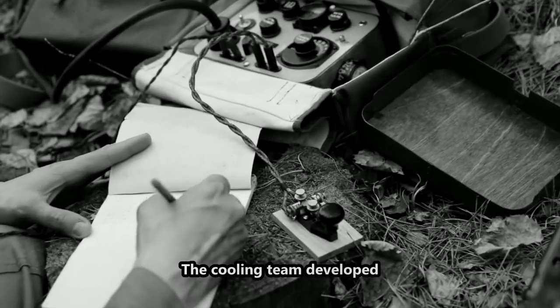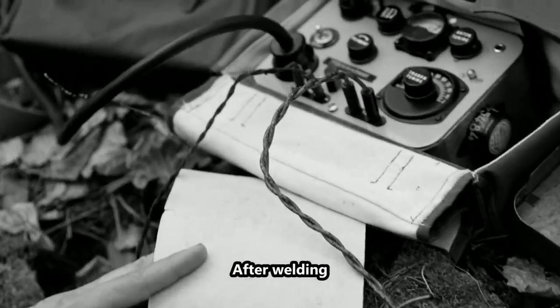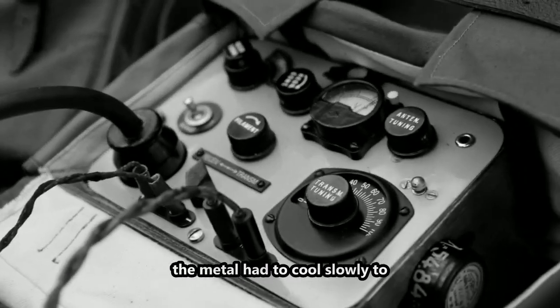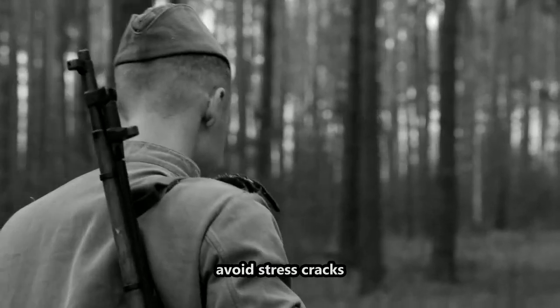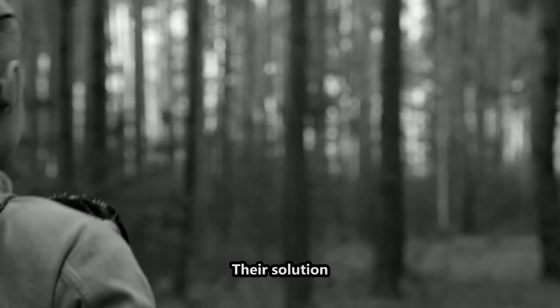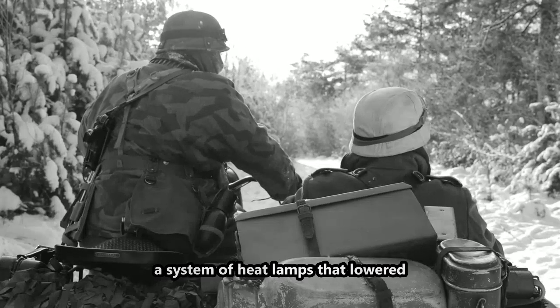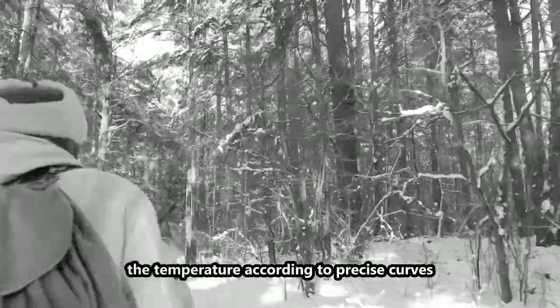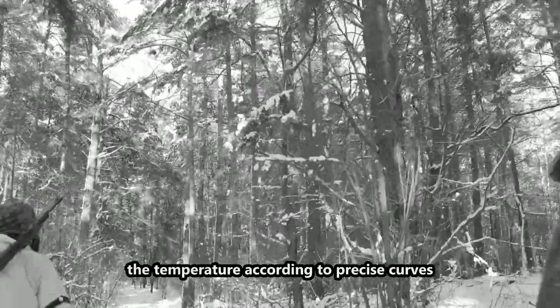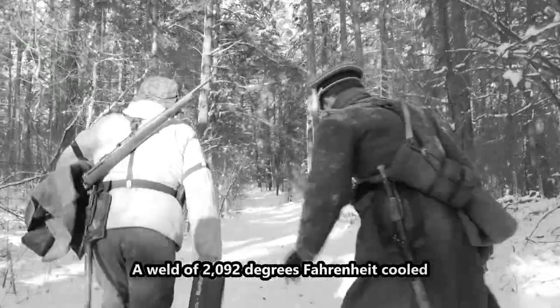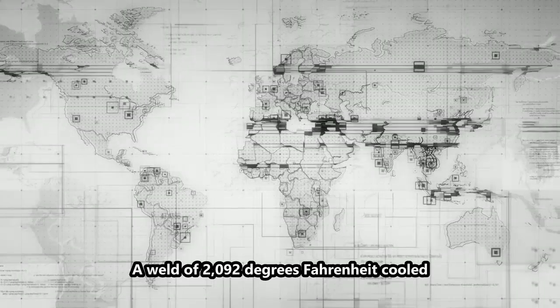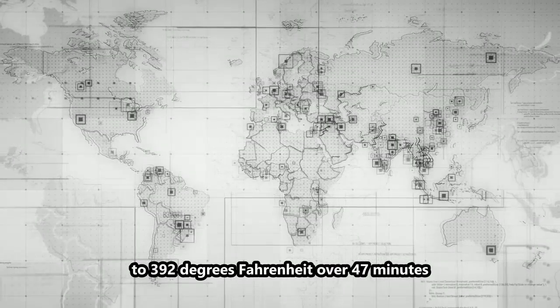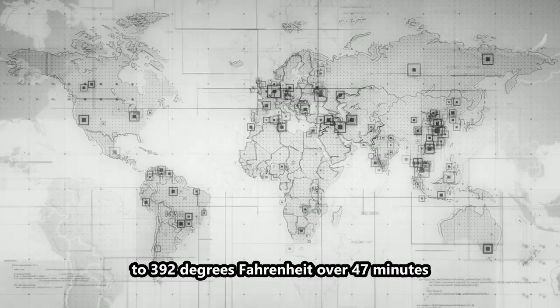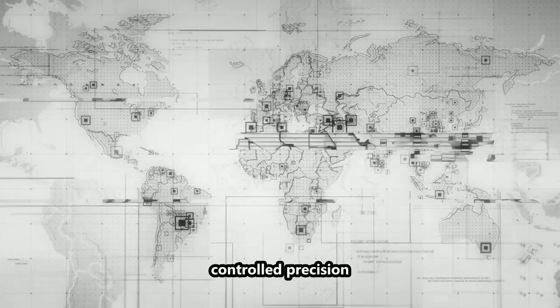The cooling team developed programmable cooling curves. After welding, the metal had to cool slowly to avoid stress cracks. Their solution: a system of heat lamps that lowered the temperature according to precise curves. A weld of 2,192 degrees Fahrenheit cooled to 392 degrees Fahrenheit over 47 minutes with computer-controlled precision.